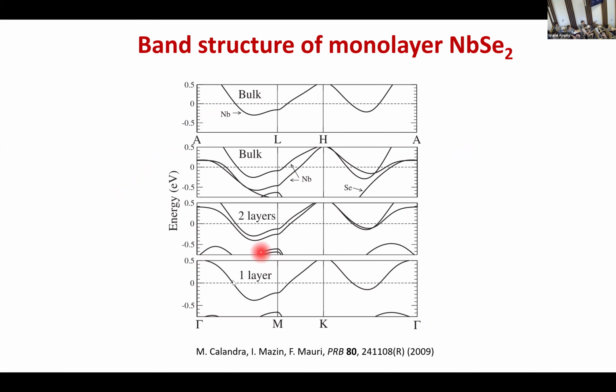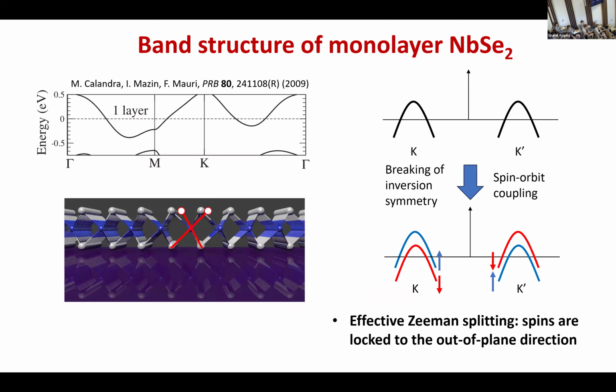These are the band structures calculated. Down to a monolayer, it looks pretty much like niobium. So these bands are mostly just from niobium. And now the band structure becomes quite simple. You have one hole band around the gamma point, and then another hole band around the K point. Let's just focus on the band around the K point. For some reason, people argue that the band around the gamma point doesn't do much. So then we focus on this band.